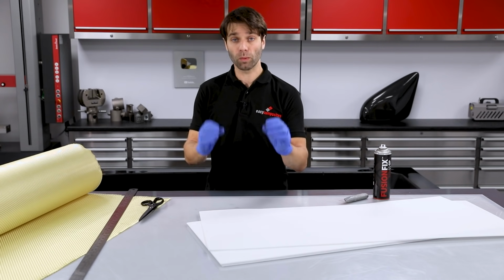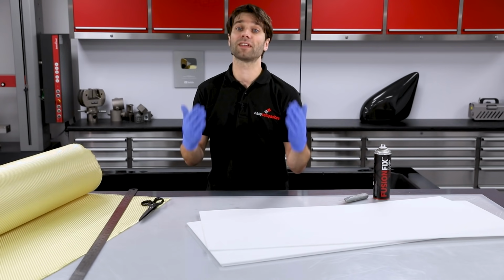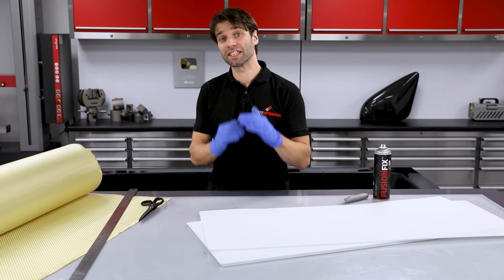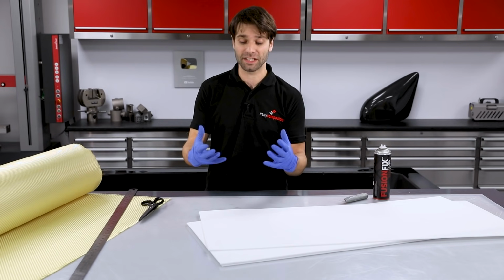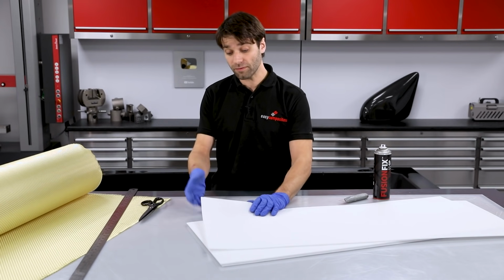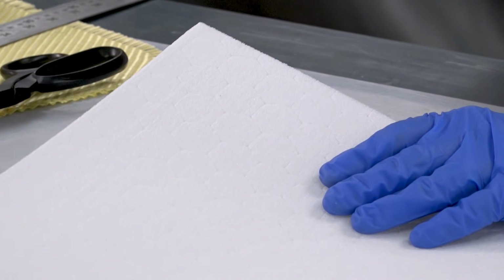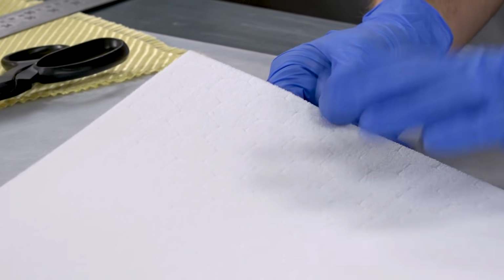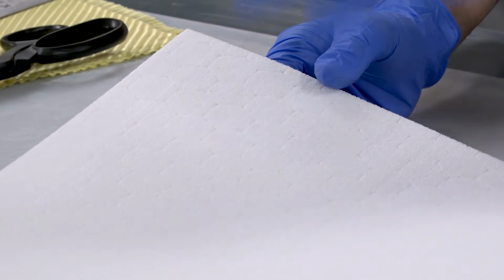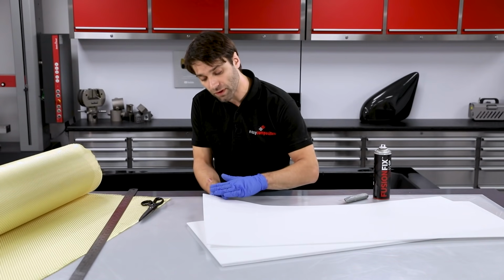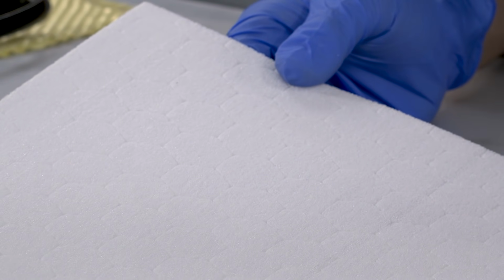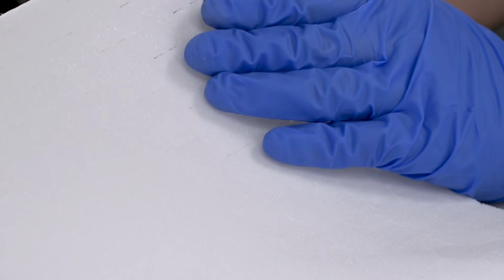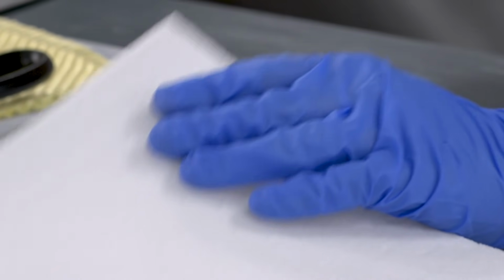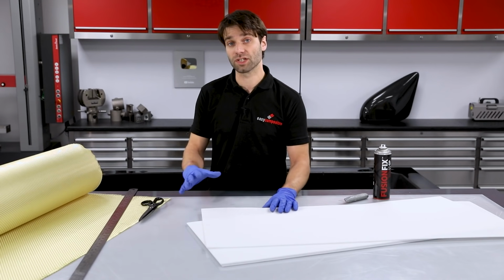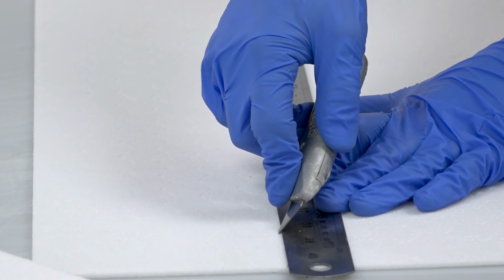core materials. Now we'll be adding a 3mm core in the flat areas of the part, and this will give us additional stiffness without adding excessive weight. The core material itself is 3D core. This is a PET foam core and it has a hexagonal pattern embossed through the surface. And this will allow the resin flow over the back to flow through the core material and fully impregnate the reinforcement behind. To prepare it, simply a case of cutting it to shape with a straight edge and a knife.